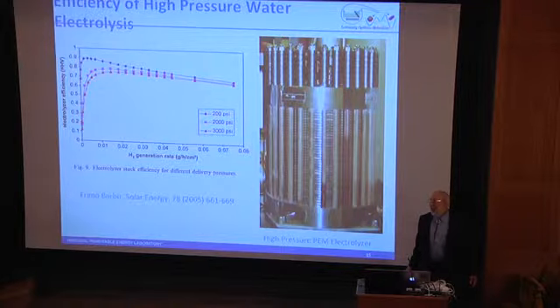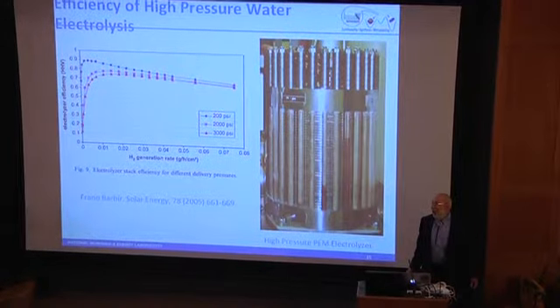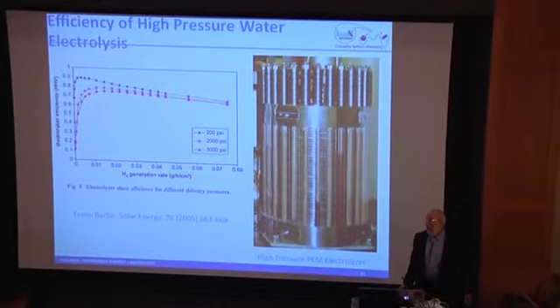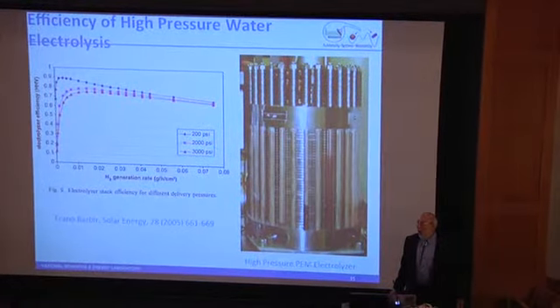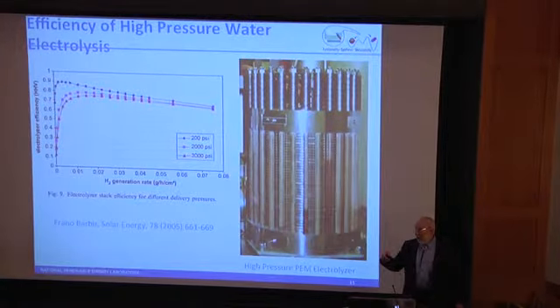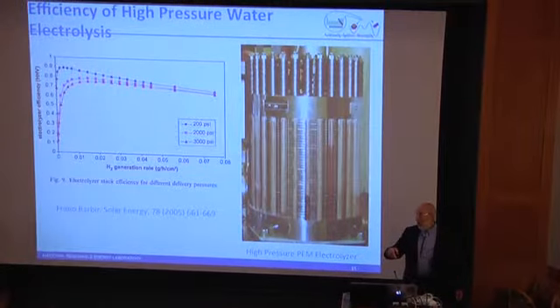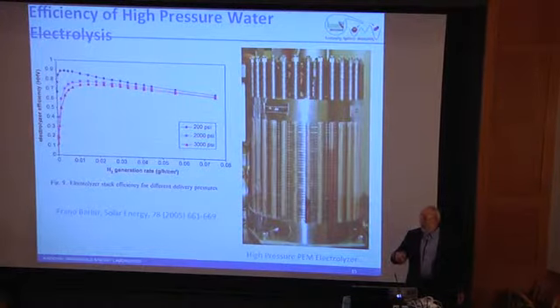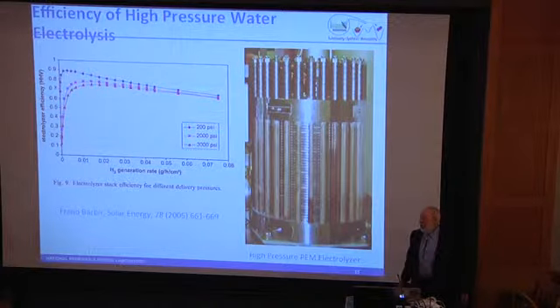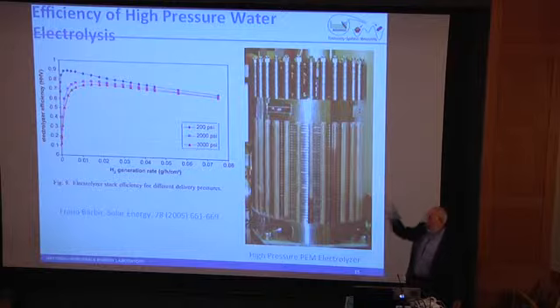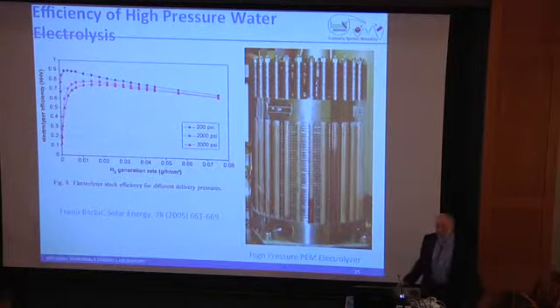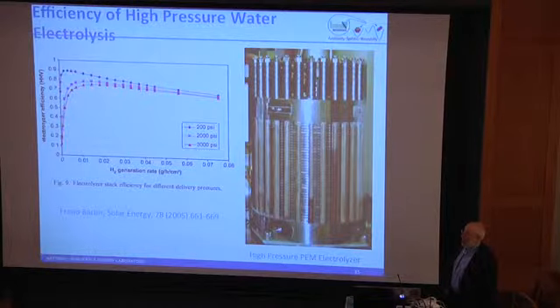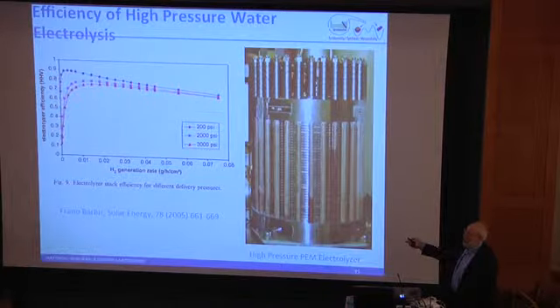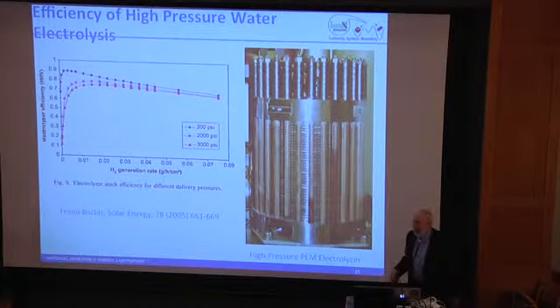Yeah? That seems counterintuitive to me because kinetics say otherwise. Once you hit an activation energy, at lower currents the overpotential is higher, but for higher currents... Well, they use a catalyst. So at low currents, there's lots of catalyst available. As you begin to push the current density, you start to run out of the ability of the catalyst to keep up with the reaction. So your overpotential actually starts to go back up. Because your loading is so high. I mean, you're talking about really staggering current densities. Right, but your catalyst loading is so low. Yeah, your catalyst loading is pretty low. Okay, thank you. Because otherwise, if you put too much catalyst in, then the cell is too expensive. Right.